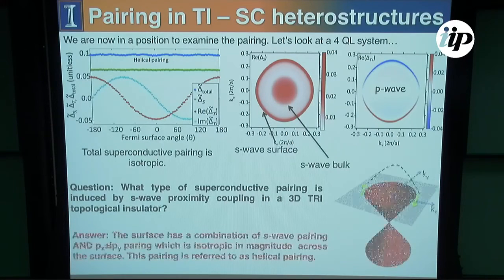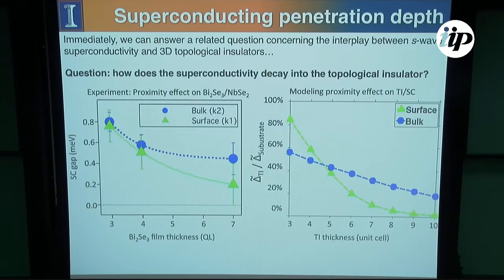So then at the end of the day, it's a combination of S plus or minus Px plus or minus iPy. But this was a nice program that we'd written, so we could ask about decay of the superconductivity into the topological insulator. And so these are the experimental results for several measurements that they did on different bismuth selenide quintuple layer thicknesses. And we see that we get basically the same sort of functional form as the experiments do.